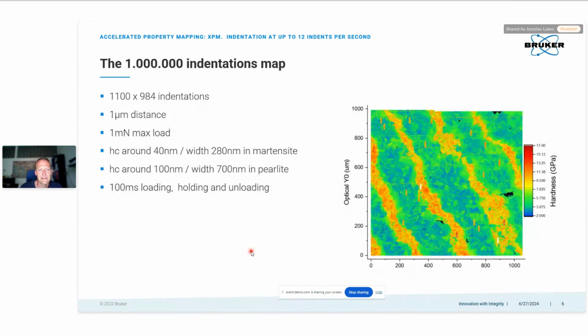So if you do everything ideally, you might get a map like this. This is the map over the Damascus steel. This map is composed of 1 million indents. You see lamellas, you see different layers. You can zoom in and also analyze the different phases that you have. These are very nice results, and I would now like to focus on the considerations behind the loading protocol that you need to apply to get such a nice result.